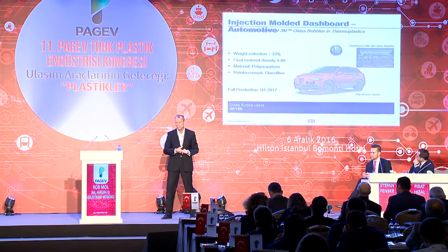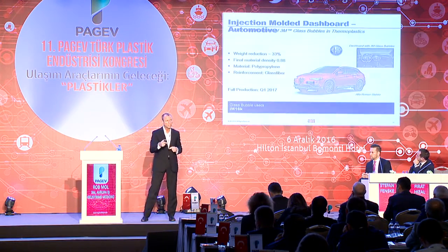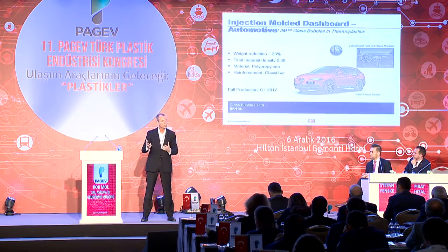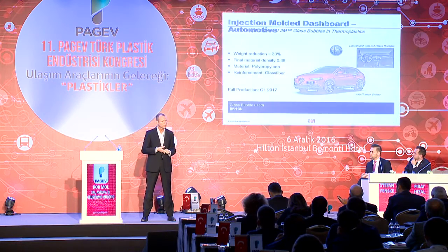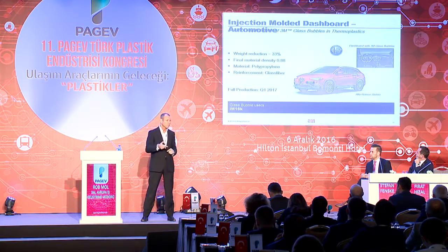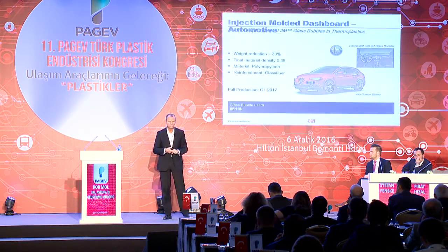But still, as you can see, and we were actually surprised about that, we always claim that you can go up to a weight reduction of about 30% with glass bubbles and still meet mechanical properties. They achieve 33%. So a real achievement.